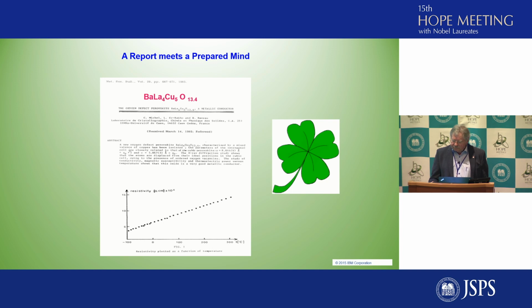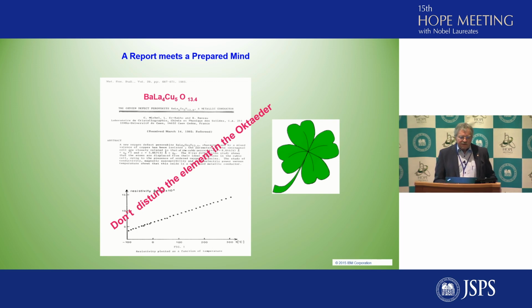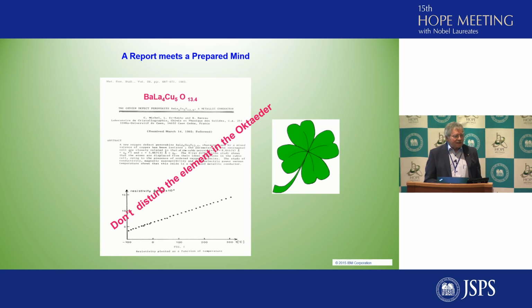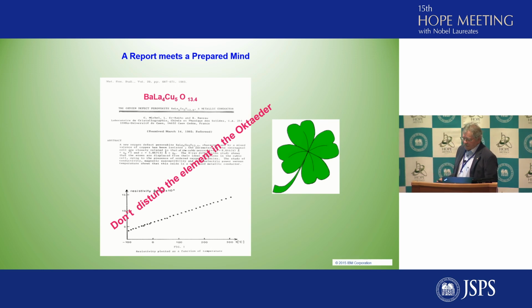So this is a pretty boring curve. There's nothing happening between 300 degrees centigrade and minus 100, so they skipped their program on these materials. For us, it was a message: don't touch the center of the octahedra, don't disturb the element in the octahedra. Just keep it stable and constant.